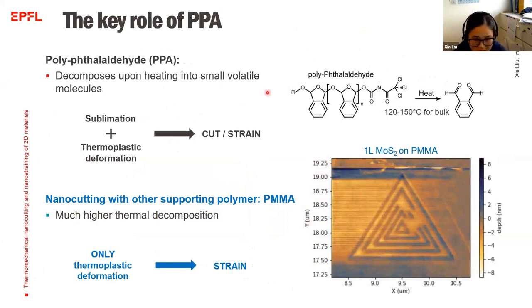So what happens during the process? Actually, during the process, the PPA will decompose into smaller volatile molecules. So in combination with the sublimation and the thermoplastic deformation, we can cut and strain the 2D materials, and both are doable. In comparison, we also tried other polymers such as PMMA. We used PMMA as a substrate instead of PPA. Only thermoplastic deformation happens, so we can only strain the 2D material. We cannot cut it. Here are some results of straining MoS2 on the PMMA. You can see the indentation depth is about a few nanometers.